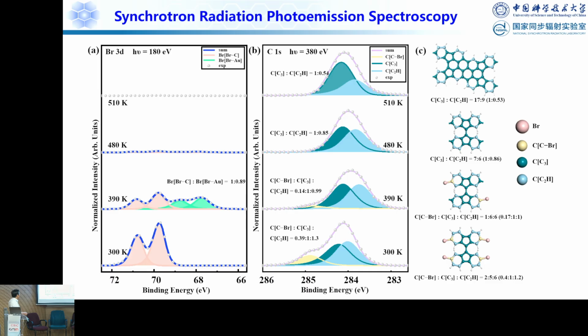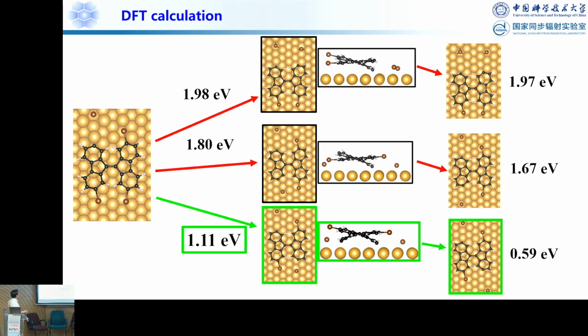Then you form this intact molecule. When you form this structure, you can see this peak intensity increases relatively. If you finally go to this, the intensity is really consistent with what we propose in this structure. And the DFT calculated results further prove that this is energetically favorable. So this is called an asymmetric debromination reaction that happened in the first step.